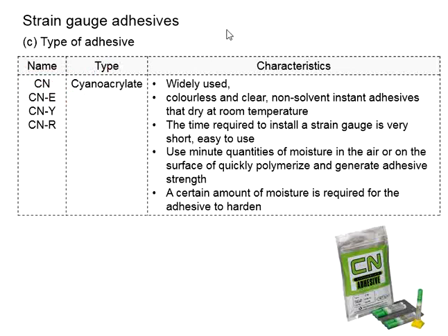This CN adhesive is a colorless, clean, non-solvent instant adhesive that dries at room temperature. The time required to install a strain gauge is very short, and this type of adhesive is easy to use. Basically, it extracts moisture in the air or on the surface of the test specimen to quickly polymerize and generate adhesive strength. Within a few seconds, the strain gauge is firmly attached to the test specimen by using this adhesive.